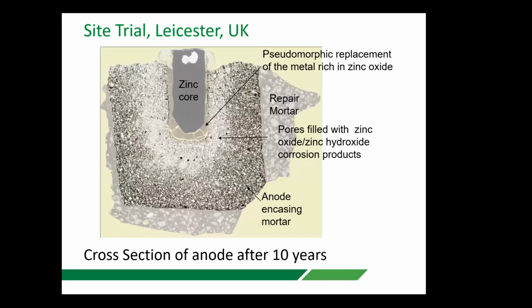Then at 10 years, we actually took out some of the anodes, not in fact the ones within the monitored area, but there were adjacent patch areas that we installed at the same time. We took one anode out to have a look and see how it was consumed. And we could see that the consumption was relatively smooth. You lost zinc. That was the original zinc outline. The space between that was evacuated, if you like, by the zinc product was filled with corrosion products, primarily of zinc oxide.